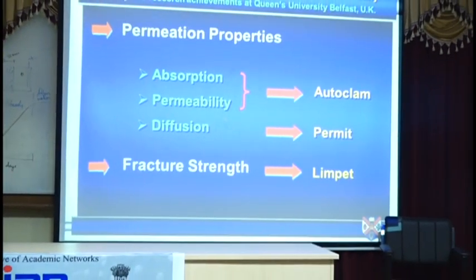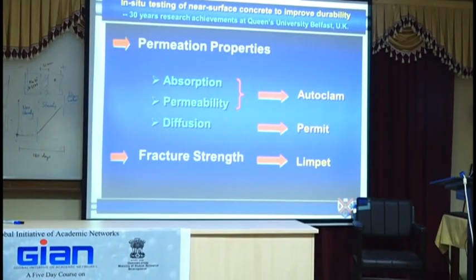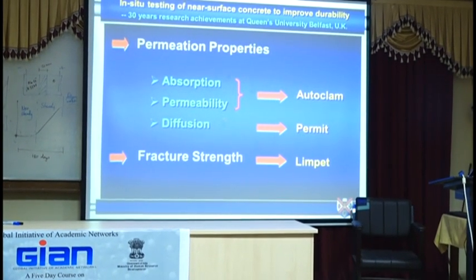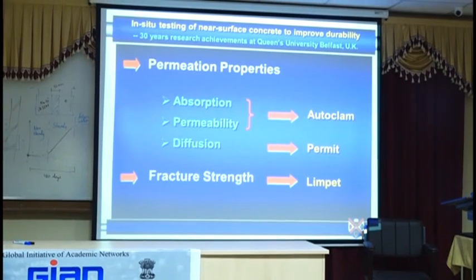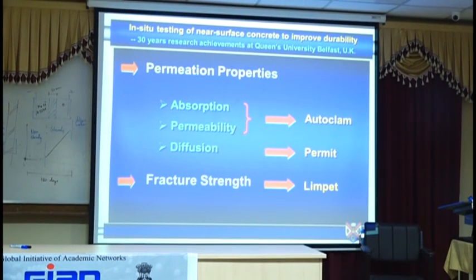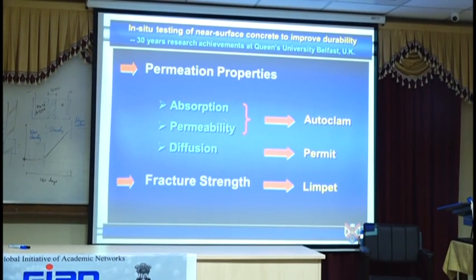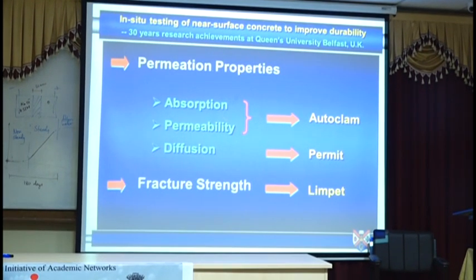Maybe I'm standing too far. They had another reason for doing this. The reason was debonding between tiles. Okay, so you have a perfect concrete surface, and then you put a tile or another surface on the top of it. They wanted to know the bond strength between the two. And that's where the test came in handy.